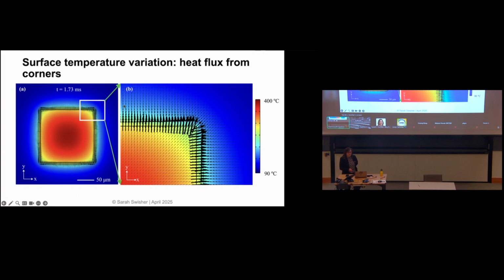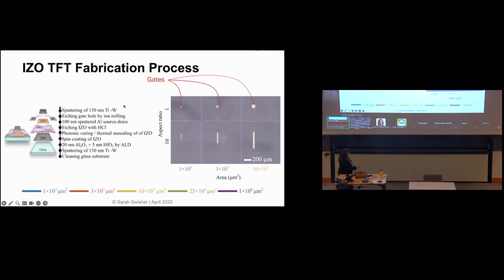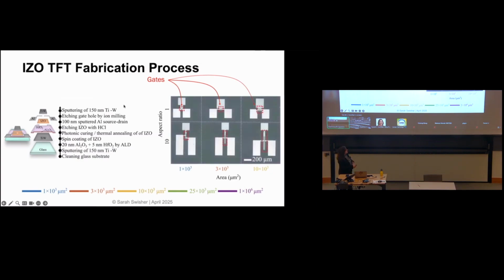So then we wanted to validate this model, so we actually fabricated devices. These are pictures of the TFT gates themselves. So we did a lot of work to try to figure out how we can design the transistors so that the transistors themselves have the same dimensions, even though the gates are going to have vastly different dimensions, so that we don't see changes in the device performance just because of channel sizes and things like that. So this is a picture of the gates. We deposit the semiconductor, we cure it, we build the device on top, and then you can see these are our 3 large probing pads, and the active devices are inside those squares there.